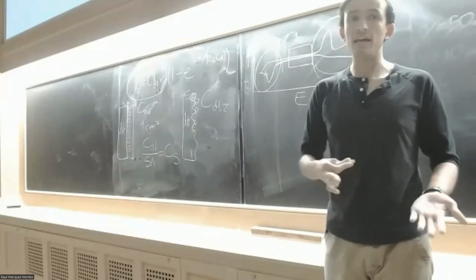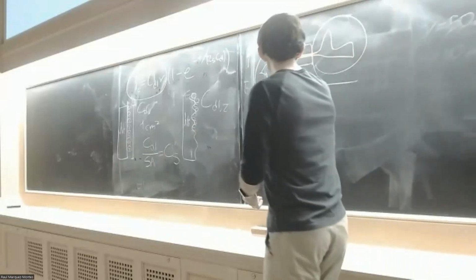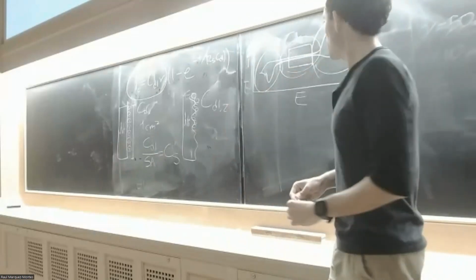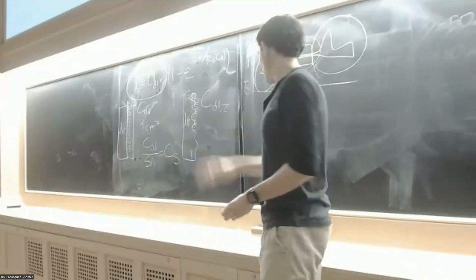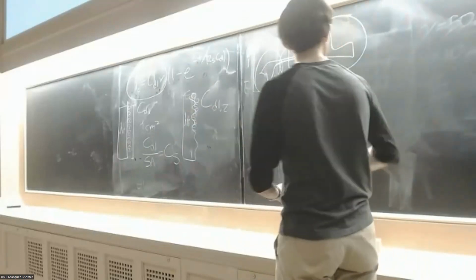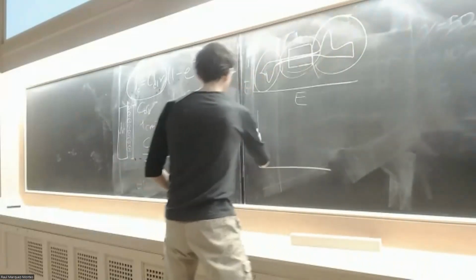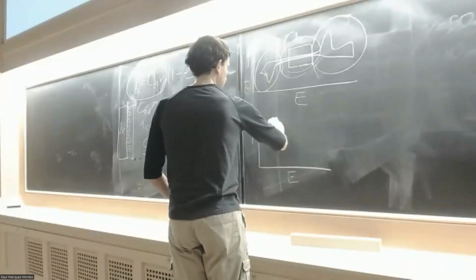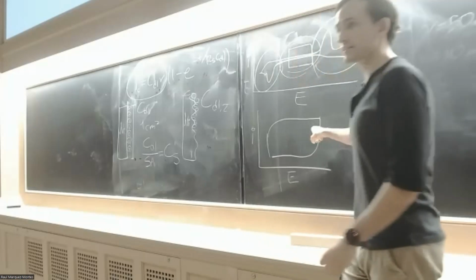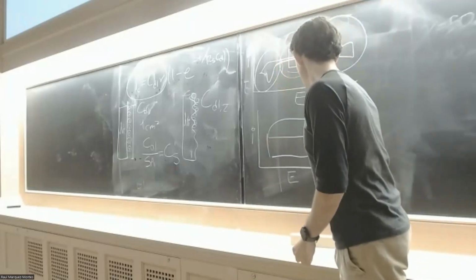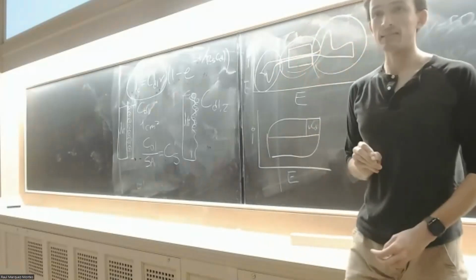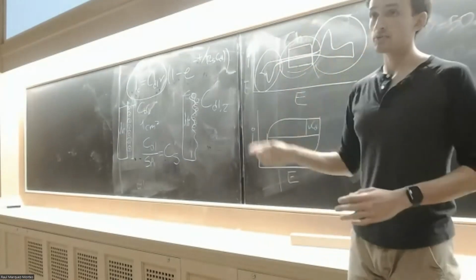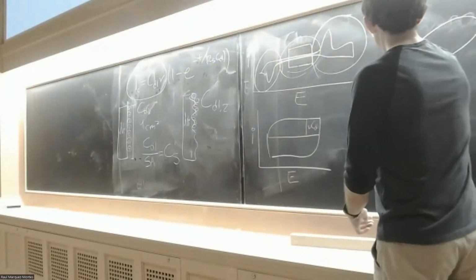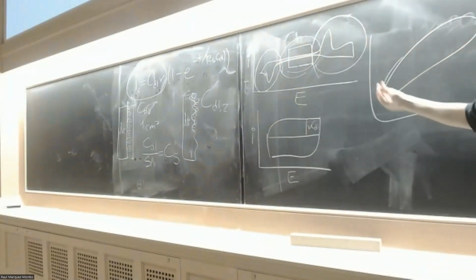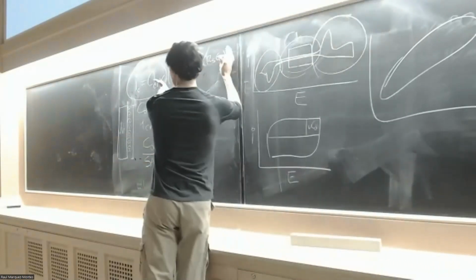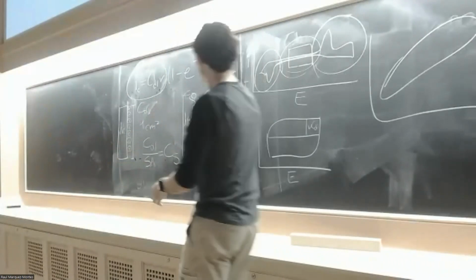So for instance, one initial step is find the best potential window, okay? Second thing, well, this is the second. Third thing, do you remember that the behavior of the curve is something like this? Like flat. Remember that this distance here was the magnitude of scan rate times double layer capacitance. Well, you need to make sure this plateau forms, because if you see something like this, well, where's the plateau? You cannot say, oh yeah, this is the part where this term becomes 0. So you need to make sure this term becomes 0.